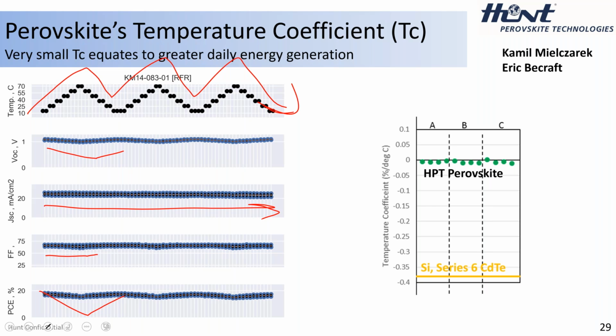So if you have a smaller thermal coefficient, you have 3 panels of equal nameplate power output, and the one with the smallest thermal coefficient will produce the most energy throughout the course of the day. So this is on the lab scale. We have not moved this up to full commercial scale, 2 meters by 1.2 meters. So there's a big fat Barry Bonds asterisk on that. However, if it persists from the lab scale to commercial scale, the perovskite panel will produce more energy throughout the course of the day than any of the competition.